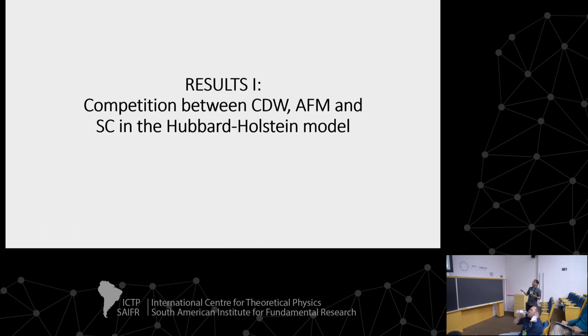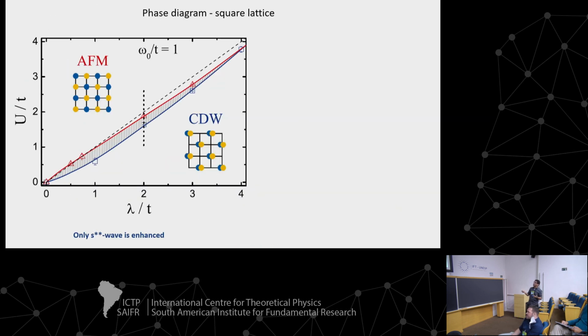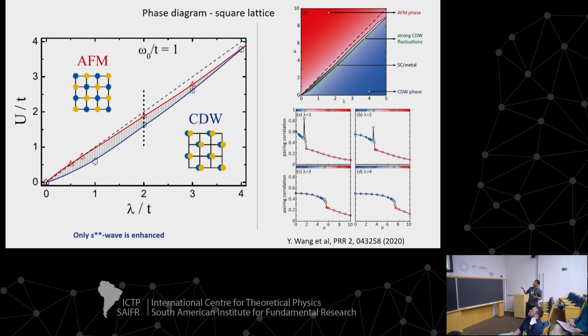But it doesn't agree with this paper from the Dendler group, in which they do a very clever thing. They perform a Lang-Firsov transformation, and then they analyze it on a 4x4 lattice, but already integrating out the phonons. So they don't have retarded effects and so on. And here they find D-wave. So D-wave is dominant in their case. But okay, this is something that's still open.